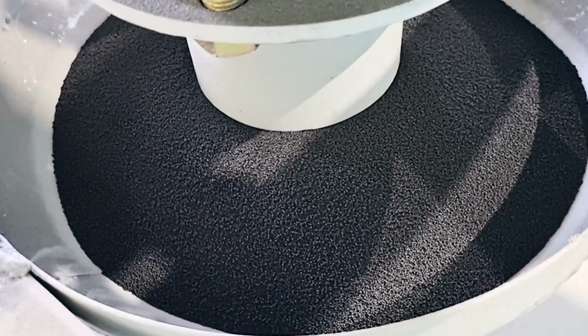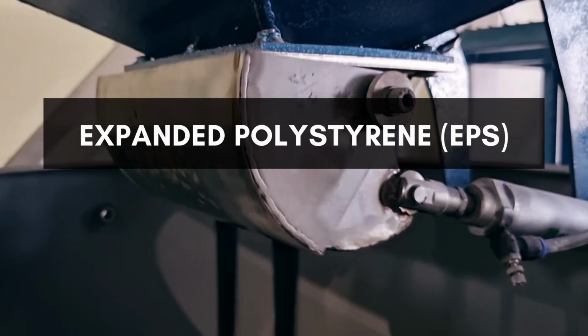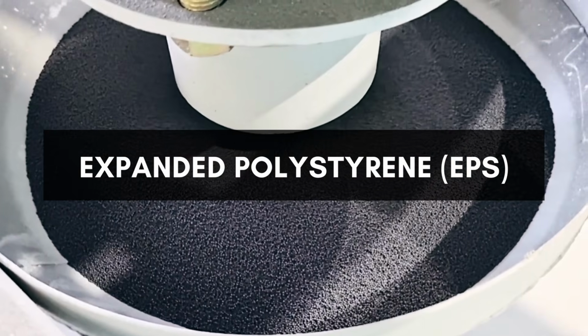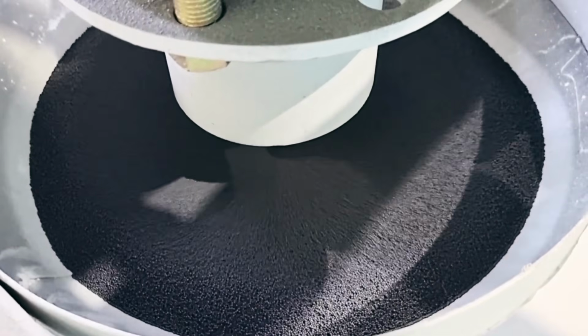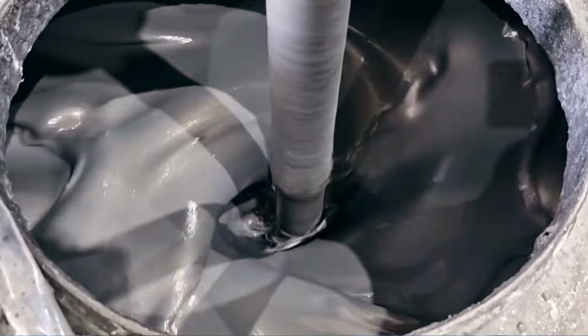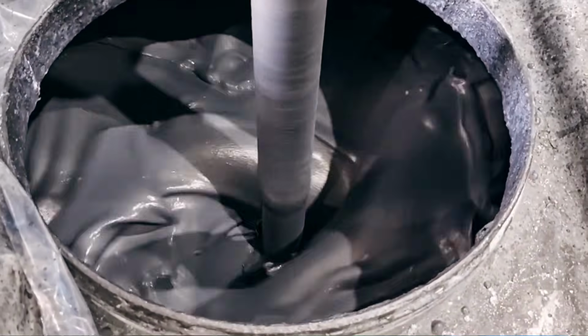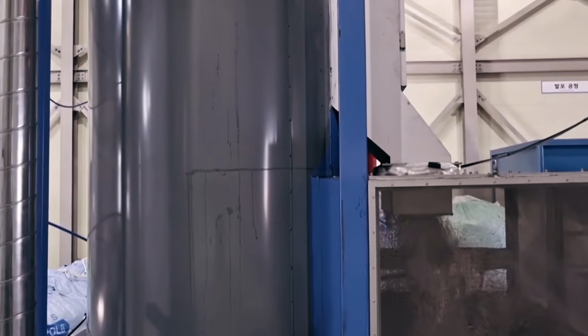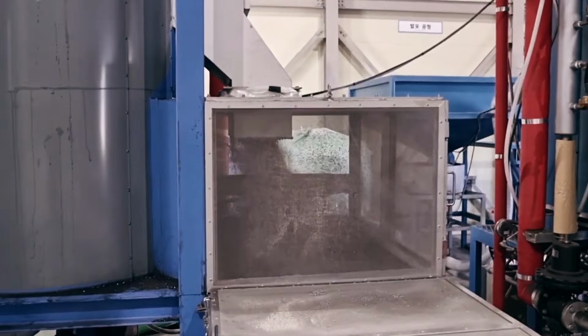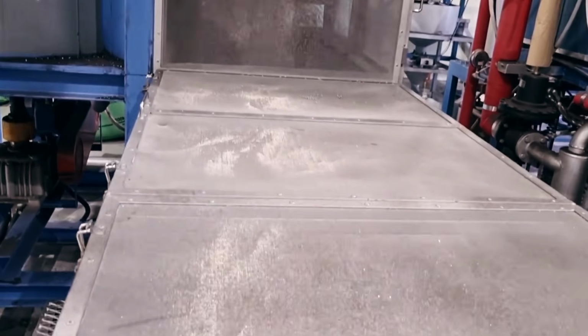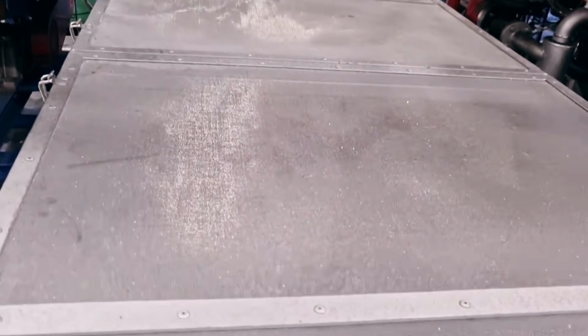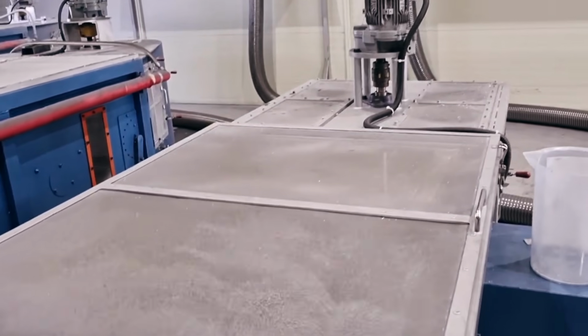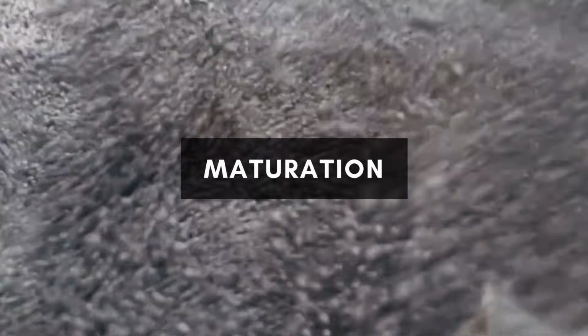Another common form of polystyrene foam is known as expanded polystyrene, or EPS. EPS production starts with raw polystyrene beads that are mixed with a blowing agent, usually pentane. In a pre-expander machine, steam is introduced, causing the beads to swell up to 40 times their original size as the pentane inside them heats up and expands. After this initial expansion, the beads are set aside in large bins for several hours to days, allowing the pentane to distribute evenly, a process called maturation.